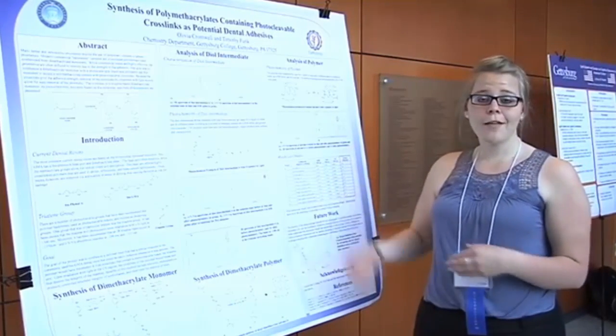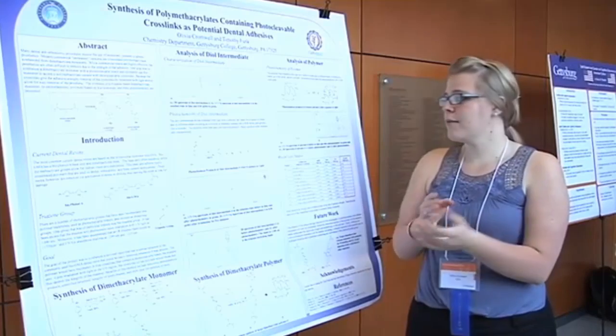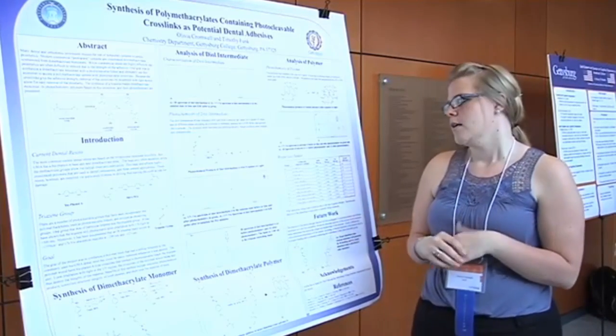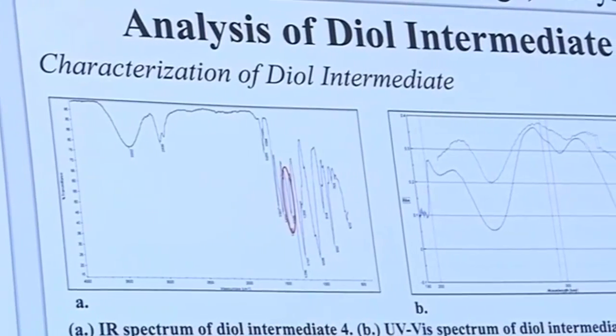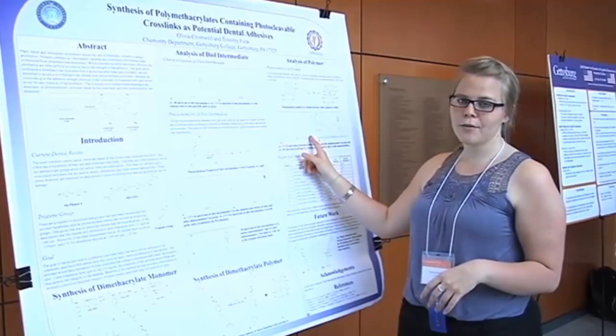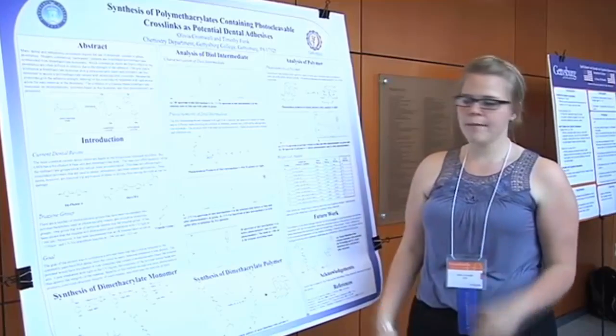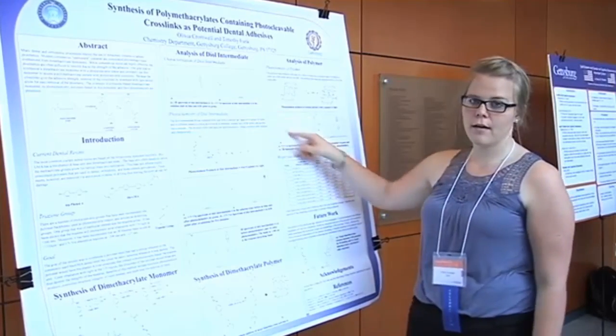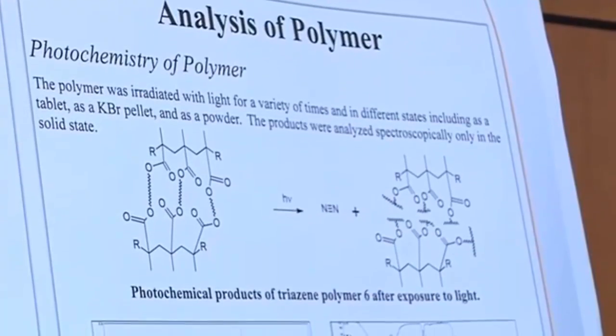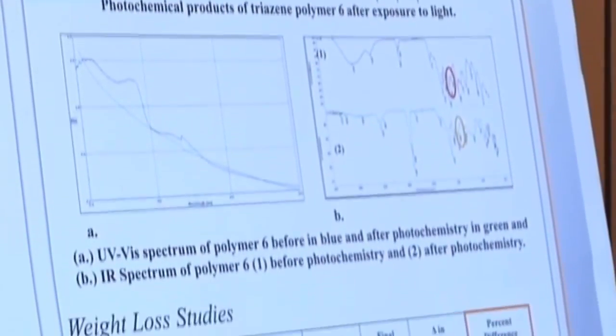Then we took our polymer, irradiated it with light, and studied its photochemical properties. We see our two diagnostic peaks before and after in the UV-vis spectroscopy at 290 and at 325. And then after photochemistry, there is no peak there. We also see it again in the IR spectrum, where there's the peak at around 1350 before, and at 1350 after there's no peak.